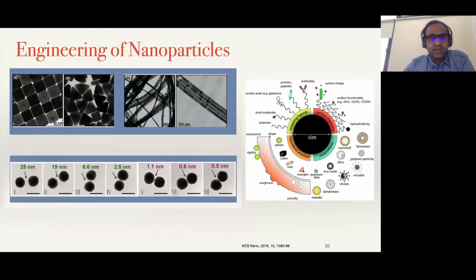So if you look at these nanoparticles over here, I've talked about silver nanoparticles, how you can actually control the shape of the silver nanoparticles. And somebody would say, what is the relevance of that? Well, if you control the shape of the silver nanoparticles, you can actually control the internalization of these nanoparticles inside the cell. So if you're looking at it from an application point of view, you can determine that cubes might undergo a better internalization as opposed to the rod-shaped silver nanoparticles.